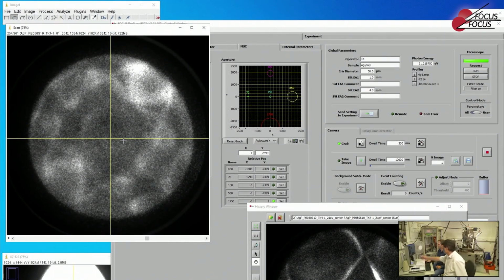Then you would choose a prominent feature in k-space which represents only one domain, or one crystallite orientation. And then this area should look brighter than the others. With the small 150 micron contrast aperture you could restrict to this small feature, for example, and switch to real space and check where it comes from.